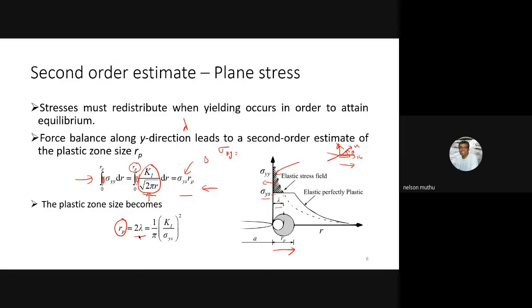Now, what are we able to see? We are able to see our model, this Irwin's methodology. This model has given us a picture that the size of the plastic zone is 1 by pi K1 by sigma ys whole square, as you see at the bottom of the slide. Then you can use the linear elastic fracture mechanics principles to solve the elastic perfectly plastic material, although it has some plasticity in it. So that is the final goal. We don't lose the plasticity, at the same time we don't lose LEFM principles. So we bring it together, and that has been brought in this framework of Irwin's methodology and Dugdale's model.